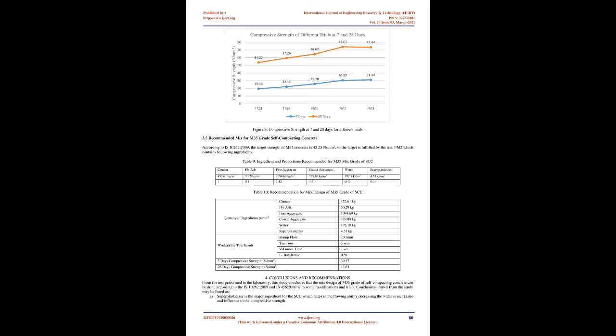From the above table it can be seen that the trials which pass the fresh property of SCC were cast and tested at 7 days and 28 days. The density of the cube was obtained above 2400 kg/m3, which is as per the IS standard. But the strength of the cube at 7 days needs to be 65% of the target value of characteristic strength. Here the 7 days strength of TRZ3, TRZ4, and FM1 was obtained less than the target strength, 28.11 N/mm2. But trials FM2 and FM3 were obtained to be more than the target strength, 28.11 N/mm2. For economy, trial FM2 was taken as the best mix from the 7 days result.